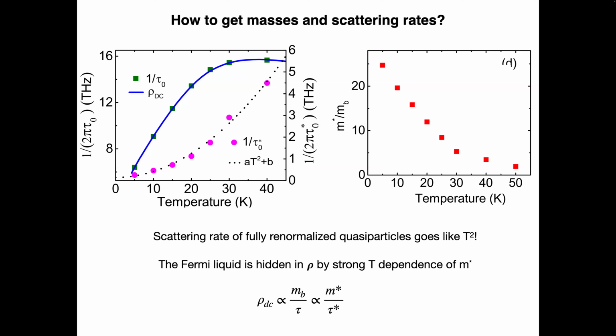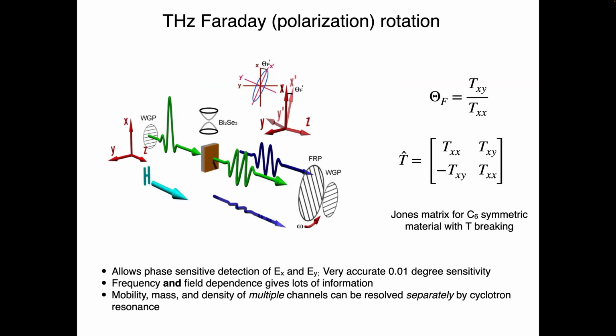It's presumably not a universal mechanism for linear in T. I don't think this is what happens in the cuprates. But in cerium cobalt indium 5, this is why the resistivity goes linear in temperature: you have a scattering rate which goes like T squared and a mass which goes like 1 over T, and so these things just cancel to give you linear in T. And again, there's not really any interpretation. It's just that the width of this feature as a function of temperature goes like T squared. And so we've called this the idea of a so-called hidden Fermi liquid.